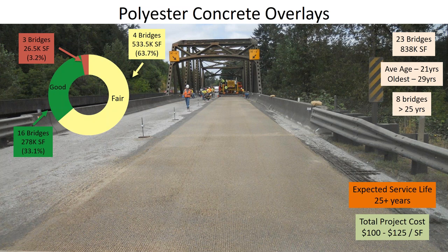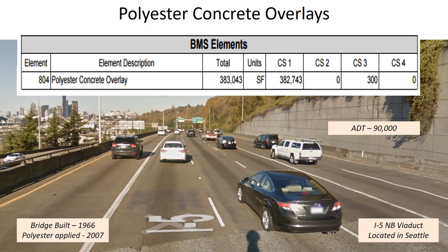The nice thing about this type of overlay, it's kind of like asphalt. It cures in about 2 to 4 hours, has a little higher project cost, but then it gives us an option for rapid construction. There's a bridge in Seattle, mainline I-5, where we did the polyester, and it's still in pretty good shape. We did this overlay in 2007. We're going to do the other direction southbound in a couple of years.